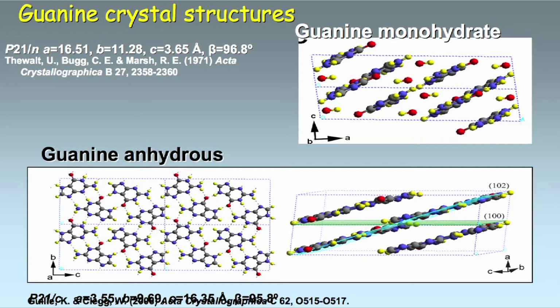But what is the real structure that makes up the crystals in fish became clear only a very short time ago. And in fact, it was after we had started to try to look at these structures that the anhydrous guanine structure became known. Again, there are very strong hydrogen bonds keeping together the molecules in the plane, and very strong stacking interactions that keep the molecules together in the direction perpendicular to the planes, or more or less perpendicular to the planes.